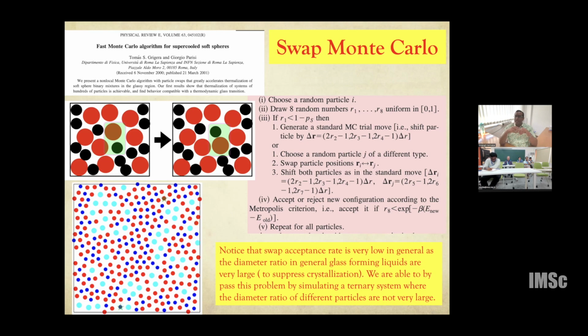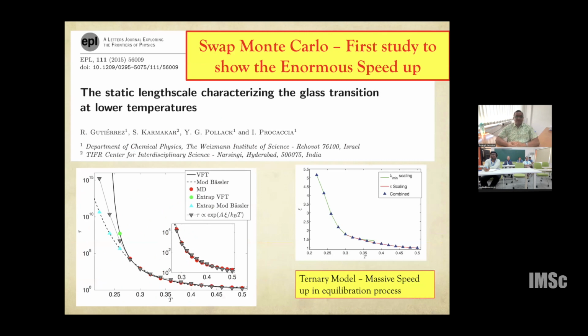So this will enhance your acceptance rate by a significant amount, and one might be able to basically equilibrate the samples much faster. And so I came back to Hyderabad, and some years went by before I actually took it up, and I discussed this with Itamar, who was my first postdoctoral mentor, and we did this work together. So we actually introduced a ternary model, a ternary glass former, and the model particle size ratios are such that this swap acceptance rate went up by at least a factor of 100.